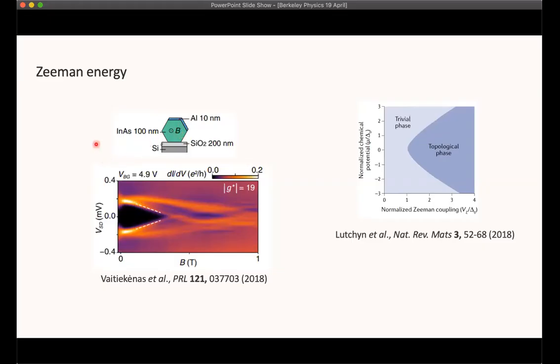And a way we can measure the strength of the Zeeman energy, which is proportional to the Landé g-factor in the material, is we look again at that superconducting gap. So now I've oriented it along the y-axis here. So you see this gap, and we see the gap close as we increase the magnetic field. So these dashed lines are guides to your eye of how the gap is closing. And so the rate of gap closing in field can be used to back out the Landé g-factor and therefore the Zeeman energy. So this is very useful to give us a sense for how we can map external fields to our place in this phase diagram.